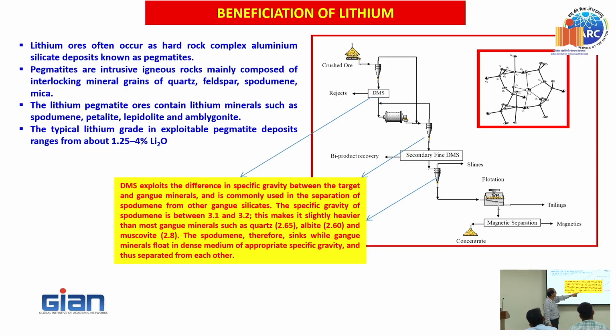Therefore, that particular thing is mixed with some material like ferrosilicon or something like that, appropriate one, depending upon the place. So the density of the suspension medium will be able to distinguish spodumene from the other minerals. So spodumene is selectively taken into some fraction, quartz, albite and muscovite are separated out. That is the first stage of separation. Then comes your grinding further. After this grinding, you have another stage of dense media cyclones. Here again further removal is there. That is followed by flotation. We use flotation.